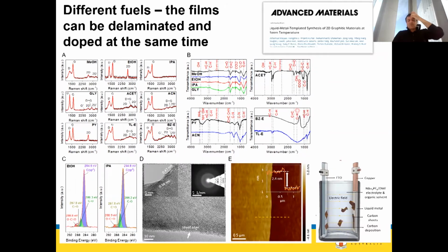But we wanted to see whether we can make graphene or graphene oxide out of this as well. So what we did, instead of letting that liquid metal deform, we just painted it on the surface of an electrode, like a copper electrode, so it doesn't deform anymore. We apply the voltage, and the voltage also helps to self-exfoliate, because electrophoresis, after it becomes a little bit thick, takes it from one side and lands it onto the other side electrode. The fantastic thing is if you use a specific precursor, for instance, if nitrogen is included in this precursor, you get nitrogen doped. If fluorine is in this precursor, it's fluorine doped. You can dope this graphene oxide material at the same time, when you are forming it.